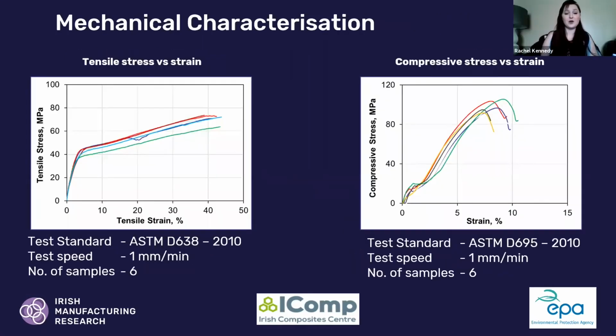I'm just going to do a quick overview of our characterization results. We have a couple of tests that are standard, that you would expect to find results of in any technical data sheet. So you have the tensile results here, and the most important part is that they're all very consistent, very uniform, nothing unusual happening. The compressive on the right does have a slight toe at the start. This is just due to settling in the fixture. The majority of the compressive strength results are in the center linear part of the graph.